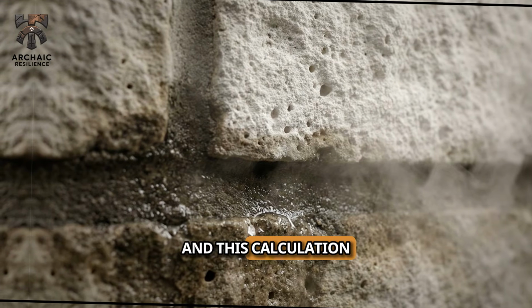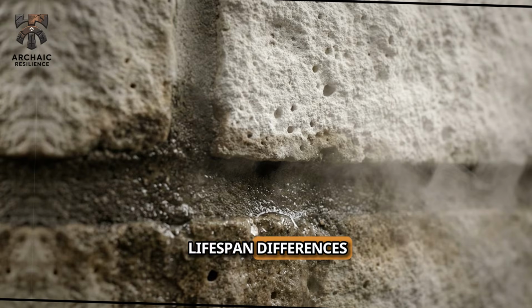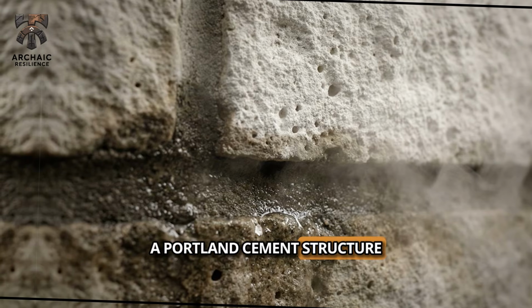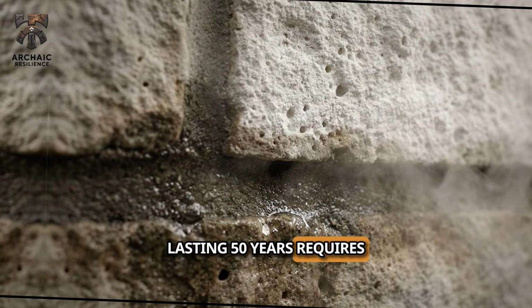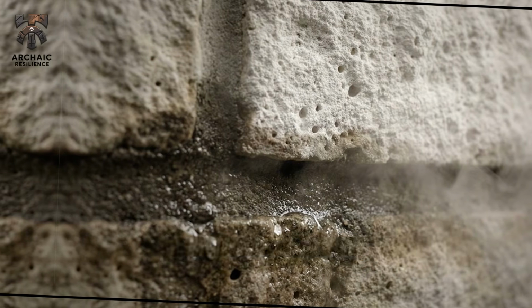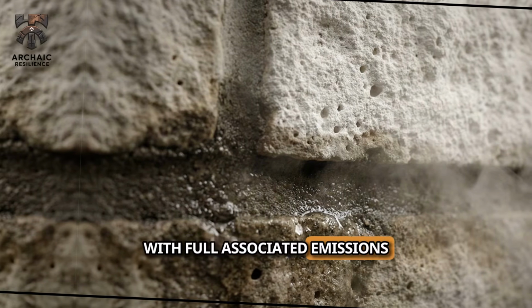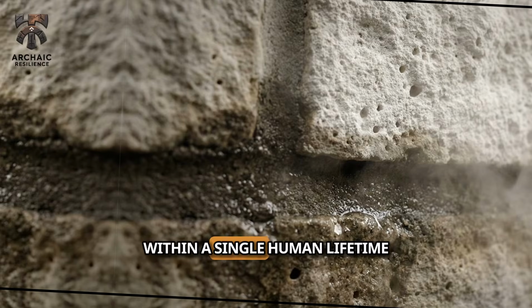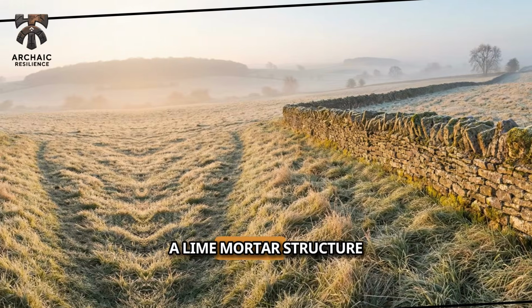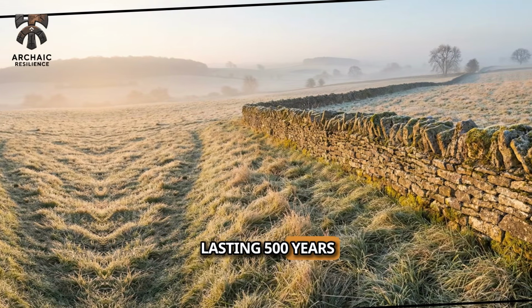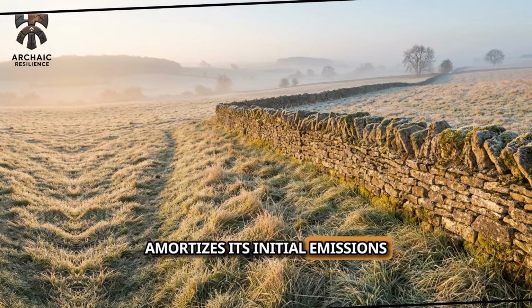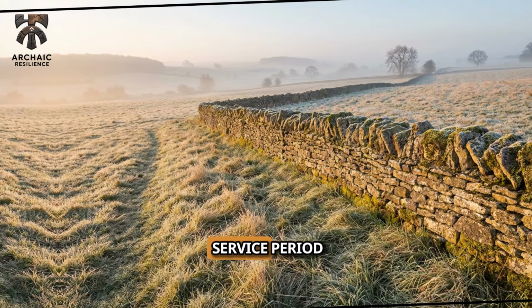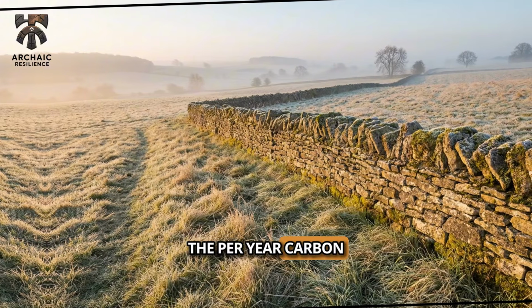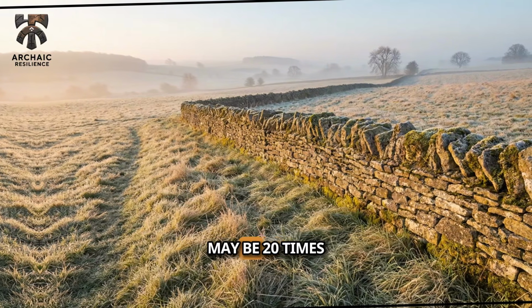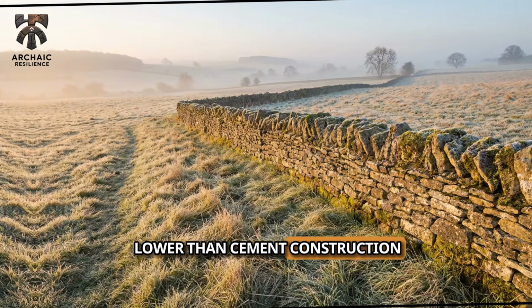And this calculation does not account for lifespan differences. A Portland cement structure lasting 50 years requires complete replacement, with full associated emissions. Within a single human lifetime, a lime mortar structure lasting 500 years amortizes its initial emissions across 10 times the service period. The per-year carbon cost of lime construction may be 20 times lower than cement construction.